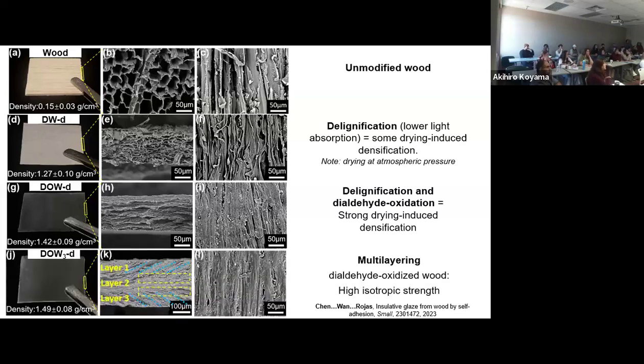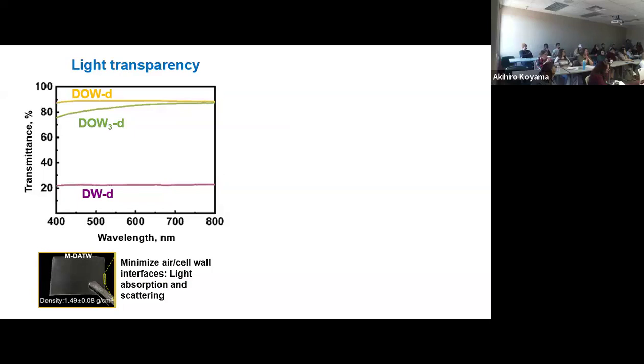And then one additional permutation. Now we don't need to be restrained to one single piece. We can have a sort of plywood-type structure with 3 layers of these pieces of wood. The transparency will suffer a little bit, but as you can imagine, this material has much better mechanical properties, right? So here: transparent, low thermal conductivity, and very strong. In this case, multi-layering. Once again, the idea is the same that I showed at the very beginning in papermaking. We add water, we remove water. That's it.